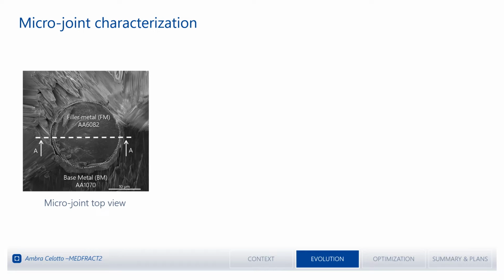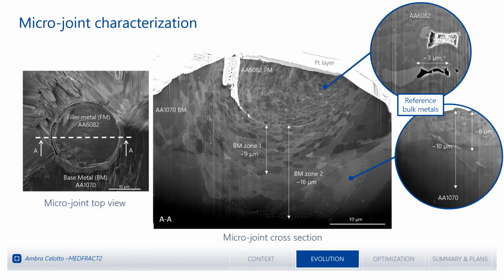And this was actually very likely to be some bonding. Watching from the top, what we can already call our microjoint, we can recognize this rounded filler metal tip that has been stuck into the base metal plate. And by doing a cross-section of this joint, we can see a quite clear bonded interface separating the two metals. And overall, it is possible to notice this quite severe plastic deformation that both materials underwent. In the case of the filler metal, this is recognizable because all the original porosities that were present in the starting material were closed down. And in the case of the base metal, the depth of the work affected area was increased by the pressure applied.